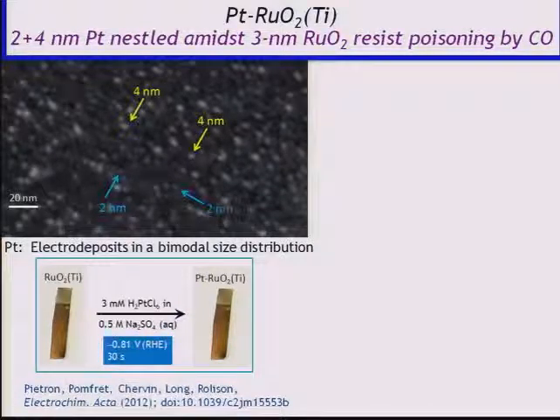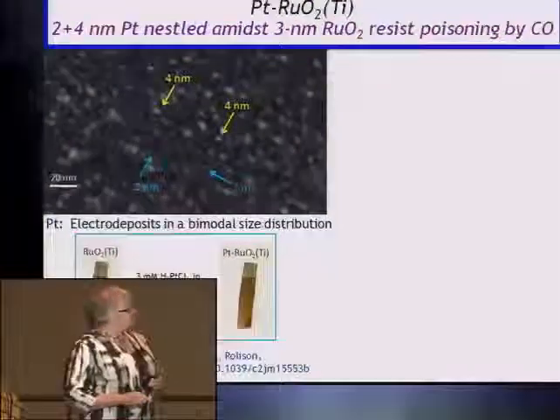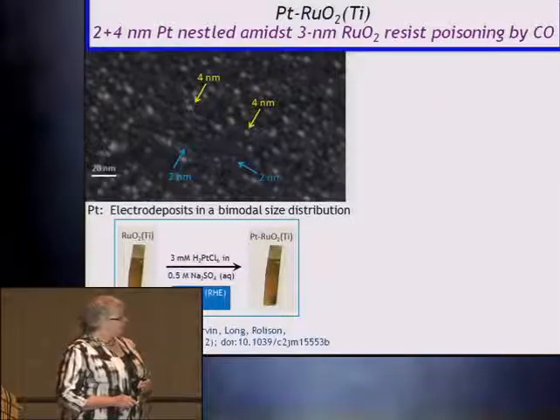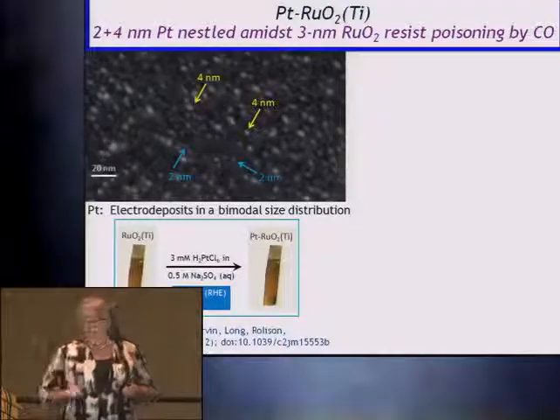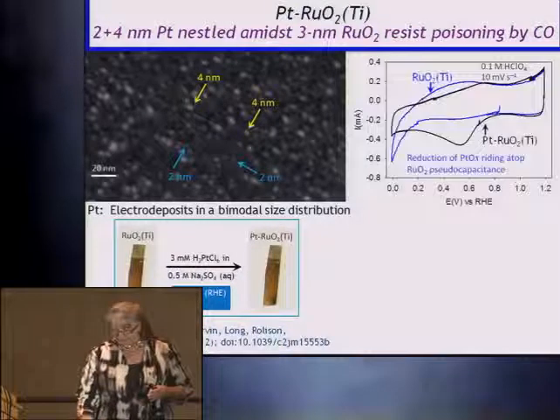So Jeremy Pietron, in collaboration with Mike Pomfret, adapted Reg Penner's electrodeposition approach to take skins of the ruthenia, now on a planar surface, titanium coupons, and deposited either about 4 to 5 nanometer bits of platinum, or extremely small, about 2 nanometer bits that you can see in a high quality image of this micrograph.